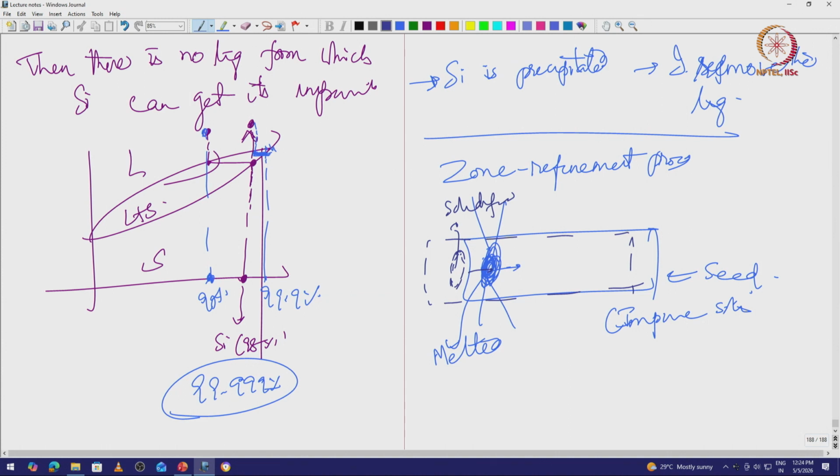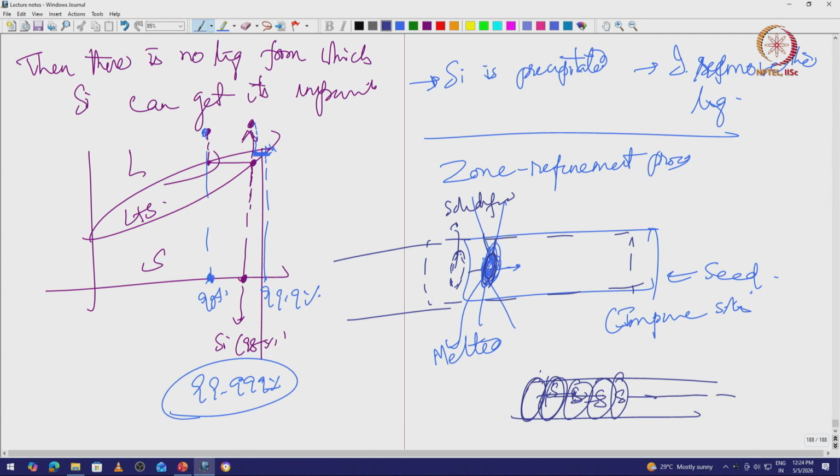So, then I am going to melt the next region. This region, let us say, is always going to get melted, and then the solid gets drawn like this. So, every part of the solid has melted, the melt is removed to the next side, this has solidified, this has melted, the melt is moved, this has solidified, and so on and so forth. So, I start melting this side, which is where I start sweeping.